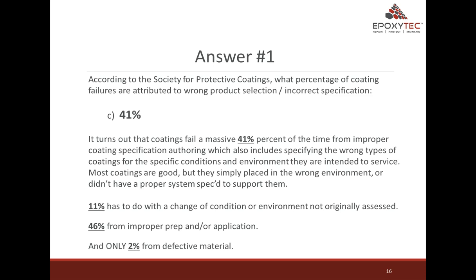According to the Society for Protective Coatings, what percentage of coating failures are attributed to wrong product selection or incorrect specification? That's 41%. It turns out that coatings fail a massive 41% of the time from improper coating specification authoring, which also includes specifying the wrong types of coatings for specific conditions and environments that they are intended to service. Most coatings are good, but simply placed in the wrong environment or didn't have a proper system spec to support them.